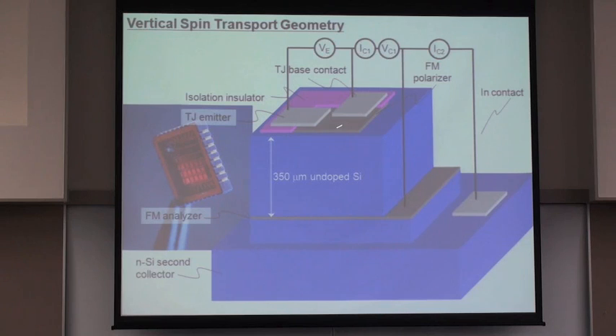we have a solid-state tunnel junction injector with a ferromagnetic cathode. We inject electrons ballistically through the anode contact, over the Schottky barrier, and into undoped silicon of several hundred microns. What we're doing is we're essentially injecting on one side of a wafer and detecting on the other side. Then after vertical transport through the semiconductor, electrons are ejected from the conduction band into the ferromagnetic metallic part of the detector, and some of them make it into an N-type silicon second collector, and that's where we measure our spin transport signal.